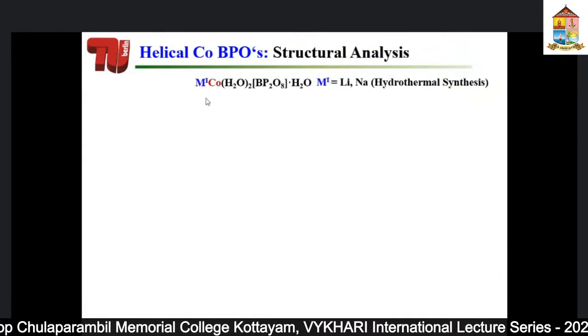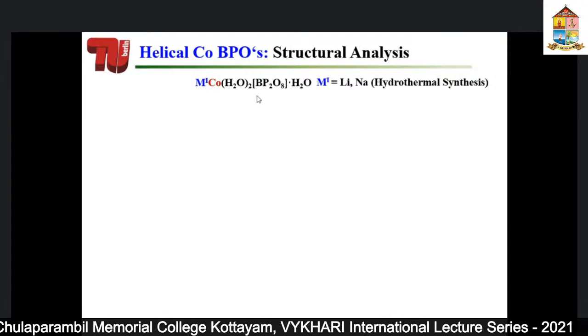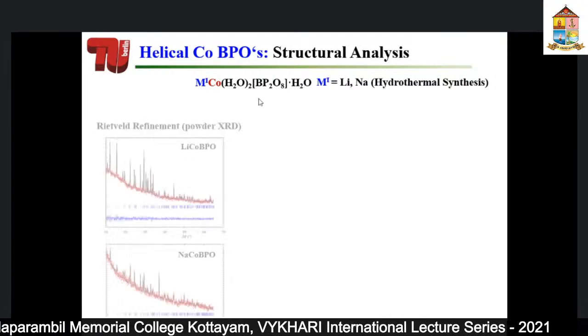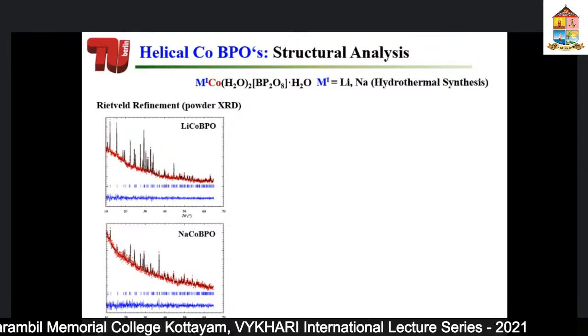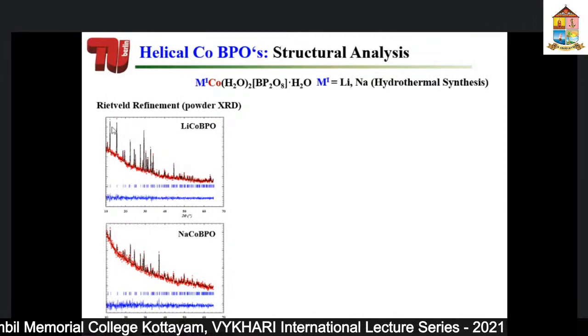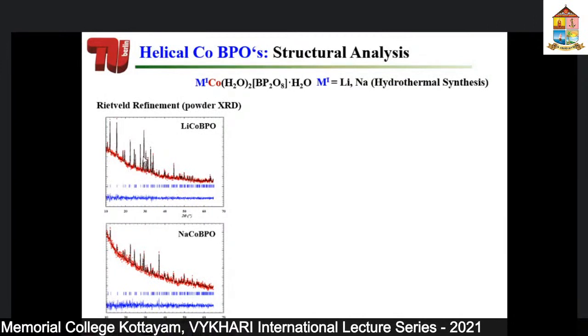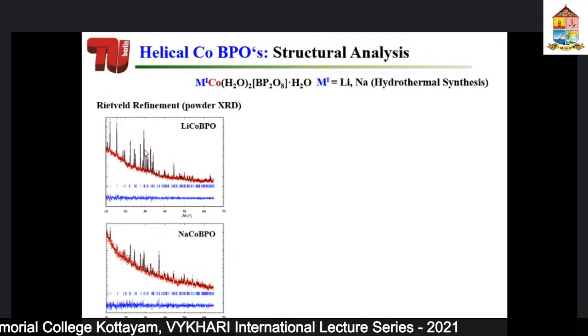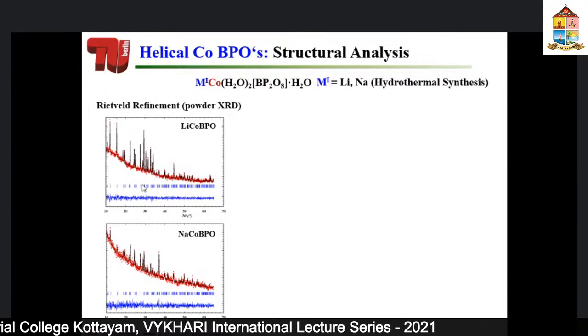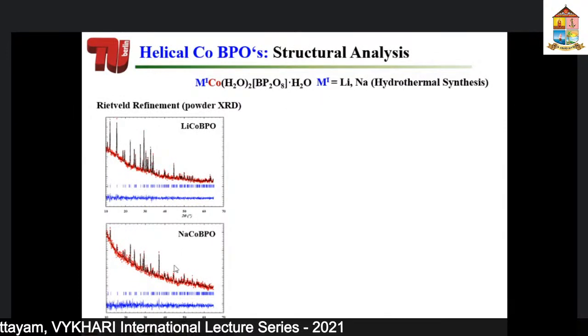So we started off with cobalt borophosphates, and this is the XRD pattern, which shows reflections meaning that our material is phase pure. It is compared with the theoretical pattern, and we have phase purity for both lithium containing helical borophosphates as well as sodium containing helical borophosphates.